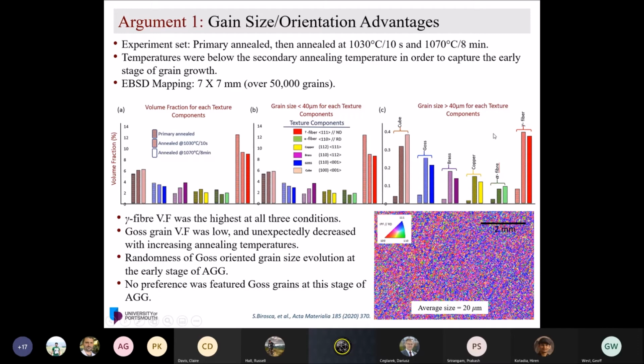What we found out, if we look at the first chart, I'm showing the volume fraction of each of the texture components. For example, Goss in blue, cube in beige, brass in purple, copper in yellow, and so on. I'm showing the primary annealed one in a dashed bar, the dotted one annealed at 1030, and the plain one annealed at 1070.